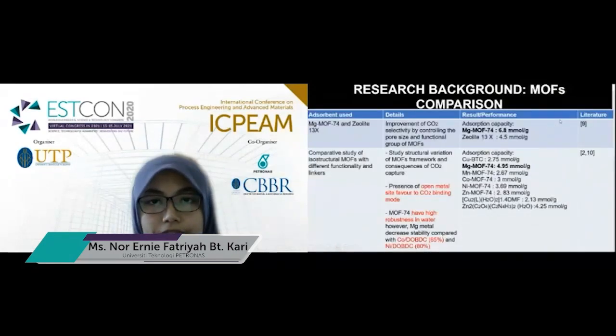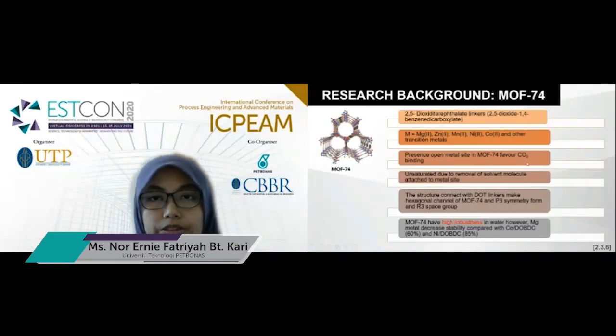There are various types of MOF, which are MOF74, zeolite 13X, MIL101, MOF5, and also CuBTC. It is reported MOF74 gives the highest adsorption capacity of CO2 compared with the other MOF due to the presence of the open metal site that favors the CO2 binding mode. And MOF74 has high robustness in water for nickel and also cobalt. MOF74 consists of DOT linkers with transition metals such as zinc, manganese, nickel, and cobalt together with magnesium. The structure that connects to the DOT linkers makes a hexagonal channel with P3 symmetric form and R3 space group. Nickel MOF74 gives highest robustness in water, which is up to 85% compared with the other metal centers.